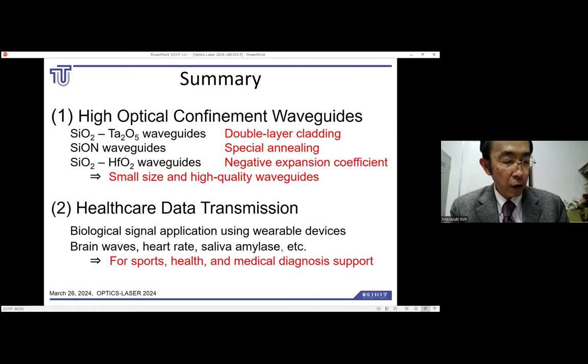First half, high optical confinement waveguides. In the silicon dioxide, tantalum oxide waveguides, crystallization was a problem, but low loss waveguides were achieved using double layer overcladding technology. In silicon oxynitride waveguides, low loss waveguides were achieved by improving the heat treatment process to reduce NH group absorption. For silicon dioxide, hafnium dioxide waveguides, a material system with a negative thermal expansion coefficient was used to enhance film stability and achieve low loss waveguides.